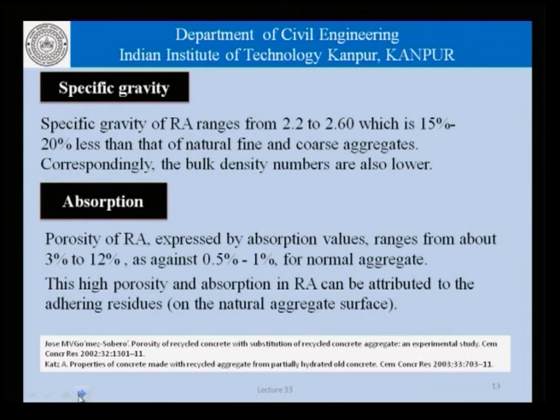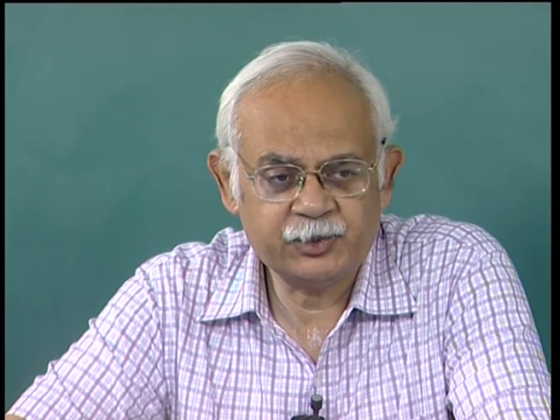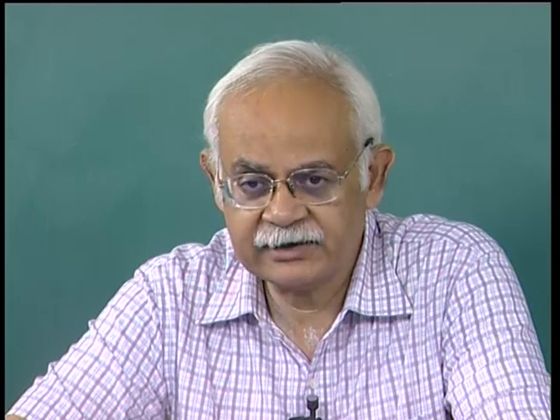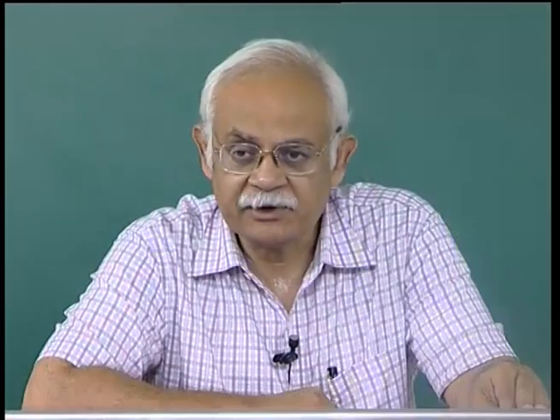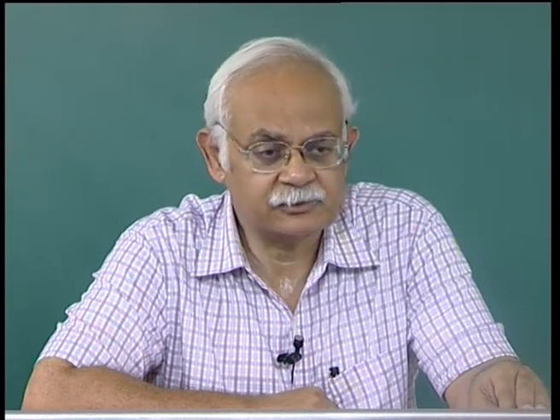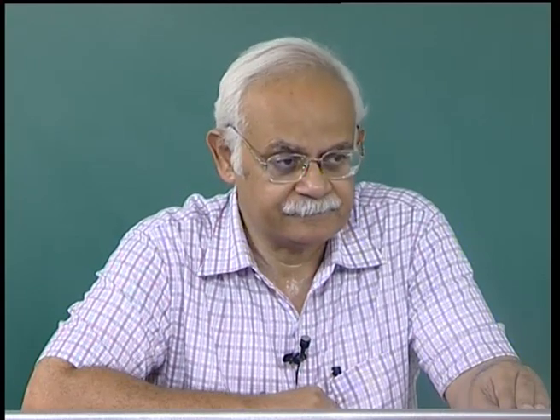Then we come to absorption. Now, the porosity of recycled aggregates expressed by absorption values ranges from about 3% to 12%, as against 0.5% to let us say 1% in the case of normal aggregates. This high porosity and absorption in recycled aggregates can be attributed to adhering residues on the natural aggregate surface. So, these contaminants which are present on the surface of the old aggregates become primary absorbers. And since we are actually evaluating the recycled material, the absorption values on the face of it increase.